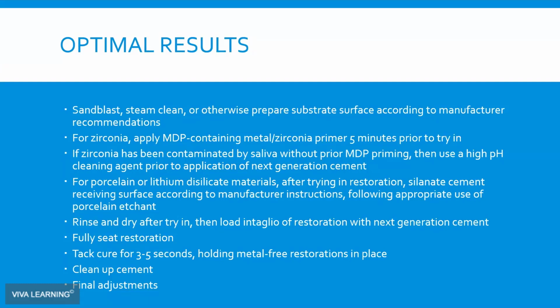But at this point, the reason I do that is because I don't like to put it on again. I don't like to clean it again because my chair time is very valuable to me. So my assistants will pre-prime it with a Z Prime, maybe hours in advance. It doesn't really matter as long as you do it at least 5 minutes before the patient shows up. Then we'll take off the temporary, clean up the preparation. I use ultrasonics to accomplish that, and then we'll try in, let's say, the full zirconia crown.